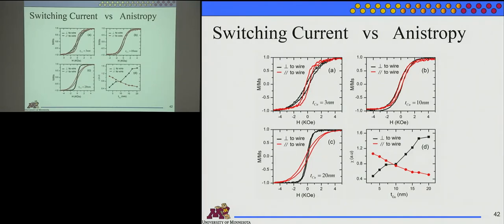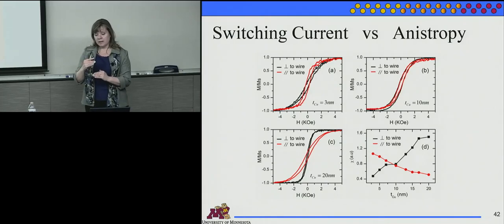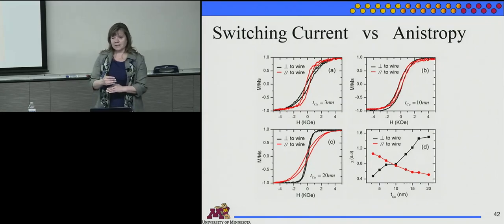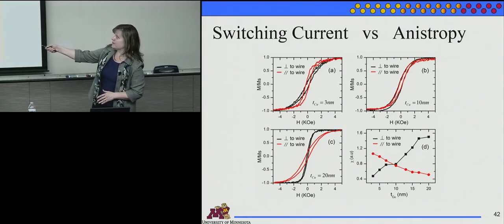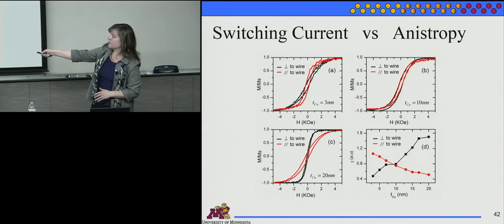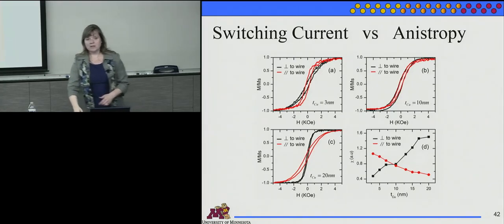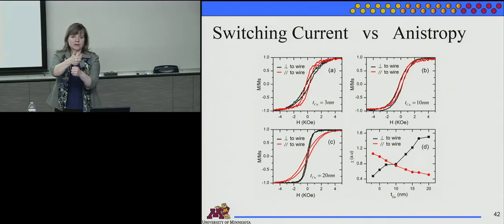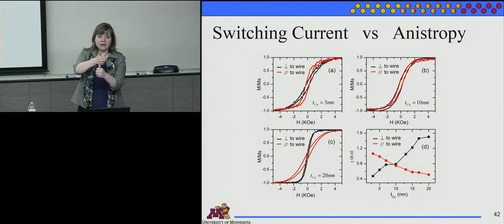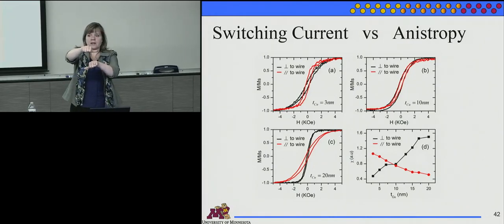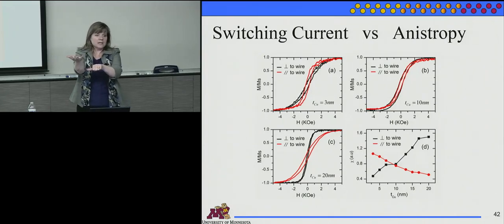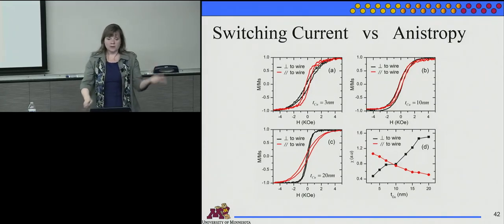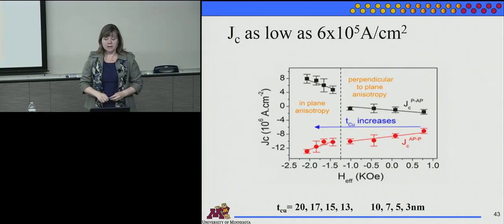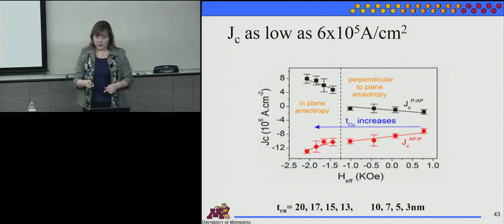So why do we see this behavior? It basically comes down to the cobalt is the same, but it's separated by more and more copper. And what happens is, this is kind of a fancy way if you want to read the VSM curves. You see, we switch from having the easy axis parallel to the wire to perpendicular to the wire. And that's because when the layers are very close to each other, they kind of stack like refrigerator magnets would stack if you bring them together. But when they get further apart from each other, they tend to align this way, and the pancake shape takes over at that point. When you switch from your anisotropies, you also switch your switching current density at where that actually happens.